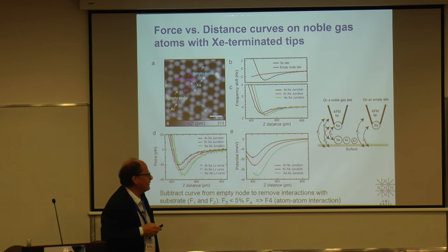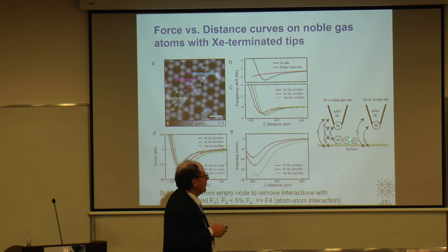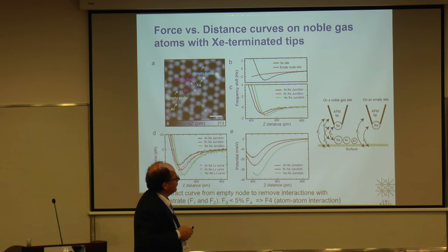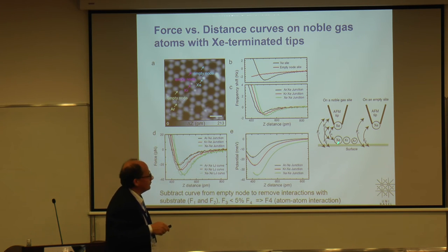You may say it may be nicer if you would measure krypton with krypton and argon with argon, but that turned out to be difficult because these tips don't like to keep them stable enough. So xenon worked, and also the xenon on this molecule network is okay, and also krypton on the molecule network or argon, but so you have basically just measured xenon with xenon, or xenon with krypton, xenon with argon. And these are the three curves, and you see that the smallest one has also the smallest maximum interaction